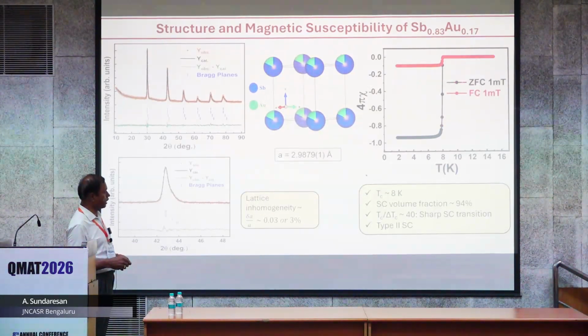When we look at the susceptibility, zero field cooled, there's a very nice transition with the 8 Kelvin TC, and the volume fraction is close to 94%. So it's bulk superconductivity. The transition is quite sharp, also demonstrating type 2 superconductor.